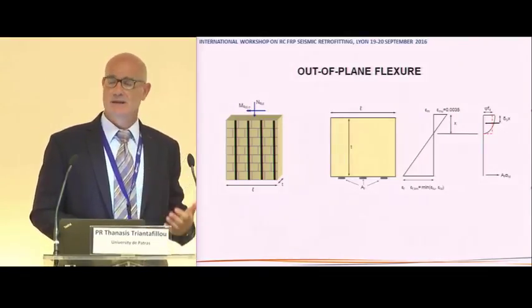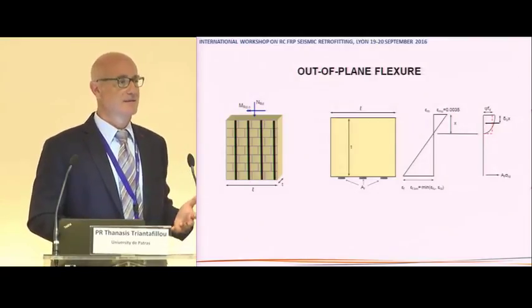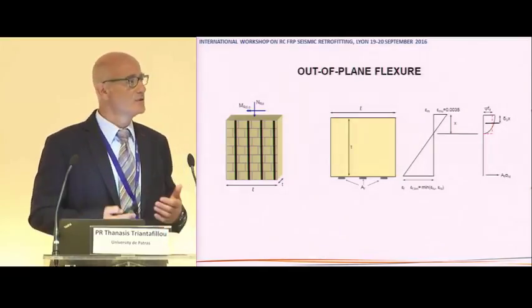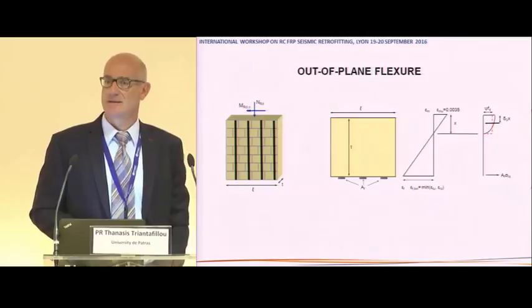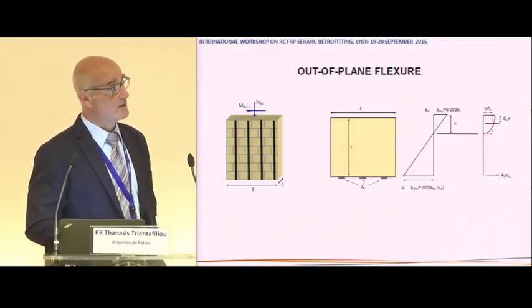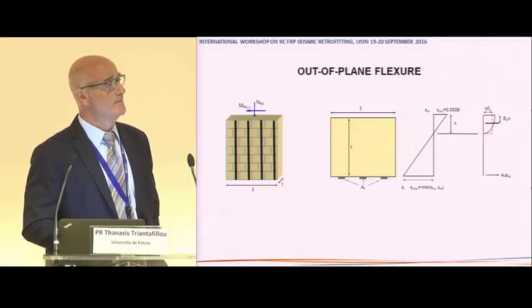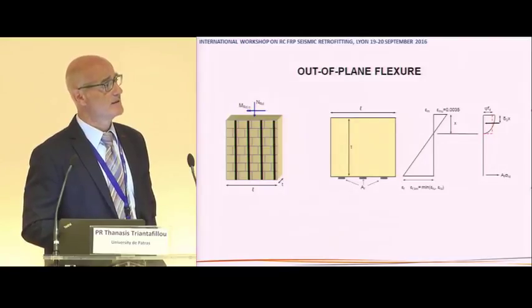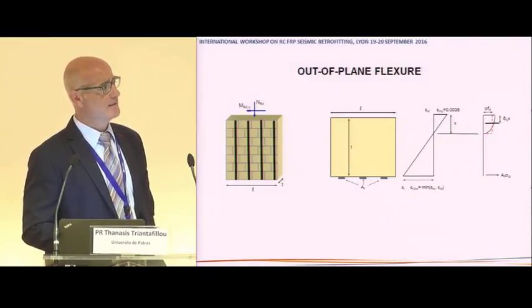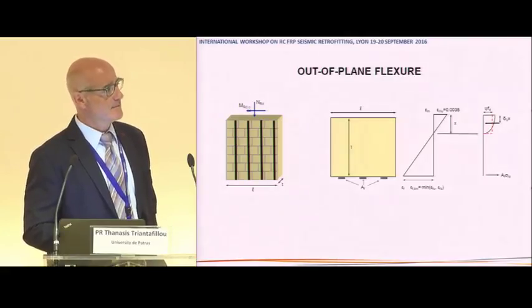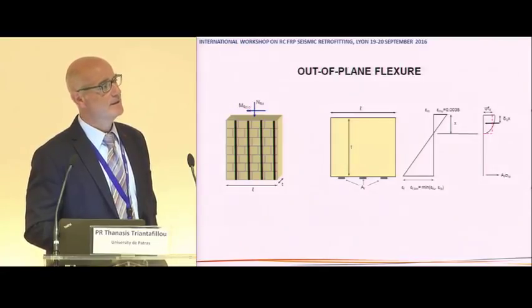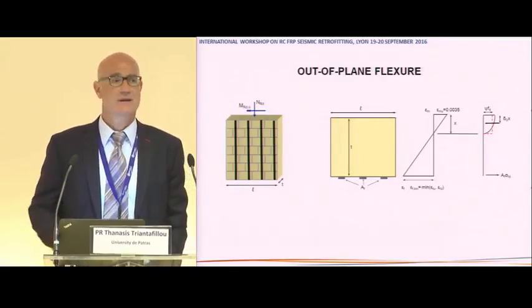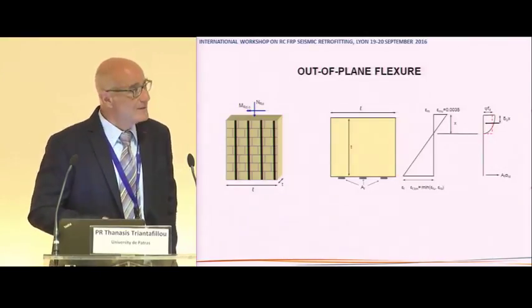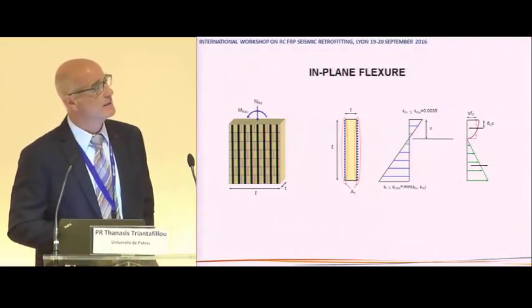We need to think of masonry retrofitted with FRPs as plain concrete reinforced, I said that before, with a non-yielding material, with a reinforcing system that does not yield. So when it comes to cross-section analysis, we can adopt models that we use for reinforced concrete. We can take a look at the distribution of strains. We have the corresponding stress profiles, and then stresses or forces carried by the fibers, by the FRPs, until something in the cross-section fails. And that is either the FRP in tension or due to debonding or the masonry in the compression zone. So this is really reinforced concrete theory applied to a non-yielding reinforcing material. Likewise for in-plane flexure.